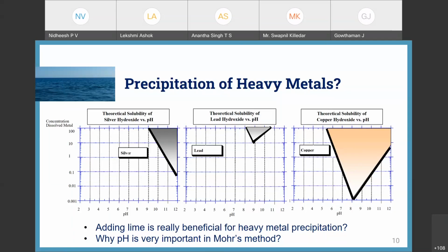And you know that in the Mohr method, it is just a discussion, or I put a question: why is pH very important in the Mohr method? We use silver nitrate and titrate against potassium chromate indicator for finding the chloride. That is the Mohr method we adopt for chloride analysis in volumetric analysis. Here pH is very important, and if you refer to APHA or any other IS standards for chloride analysis, you can see that a pH of 6 to 7, near neutral, is the optimal pH for the Mohr method. Otherwise, you will get error in the analysis.